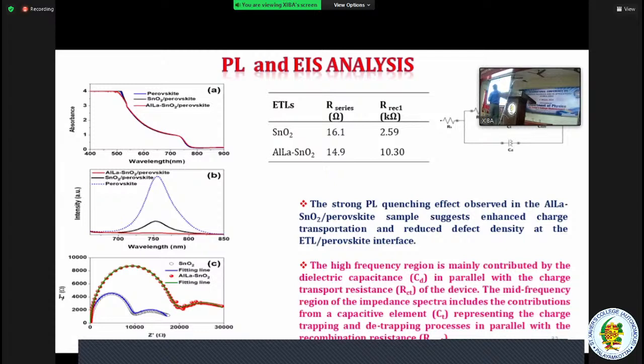Actually, these are all the values we obtained for the tin oxide ETL and the aluminum lanthanum tin oxide ETL. You see the series resistance for tin oxide is 16.1, and for aluminum lanthanum tin oxide it is 14.9. Similarly the recombination resistance is 2.59 for tin oxide, whereas for our sample it is 10.3. So it's a very remarkable value we got. Next slide.